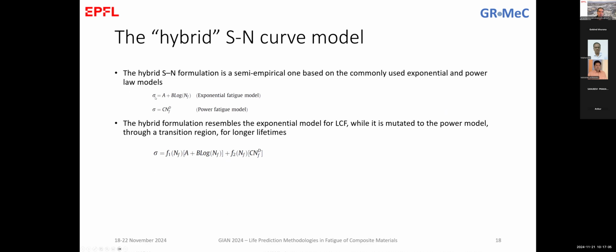So we've seen before the problems of the exponential model. Here I also show the model. This is the exponential, what we call the semi-logarithmic, and the power model, which is, if you like, the double logarithmic model. It's a line in a double logarithmic plot. And we've seen the problems that they have. One is overestimating the life at low cycle fatigue, and the other one is underestimating actually the life at